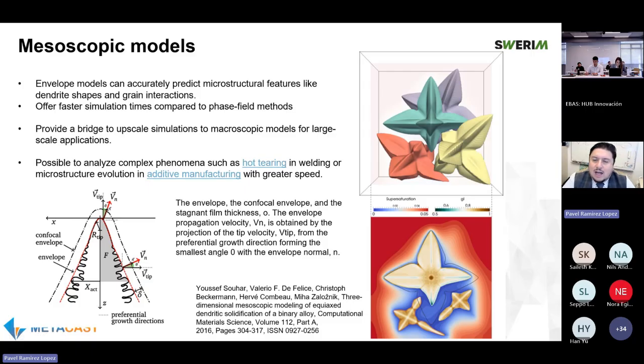Here we can see a classic envelope model, which can accurately predict microstructure features like dendrite shapes and grain interaction. So you do get these grain competitive effects. They offer faster simulation times compared to phase field methods, and it's possible to analyze complex phenomena such as hot tearing in welding or microstructure evolution in additive manufacturing.